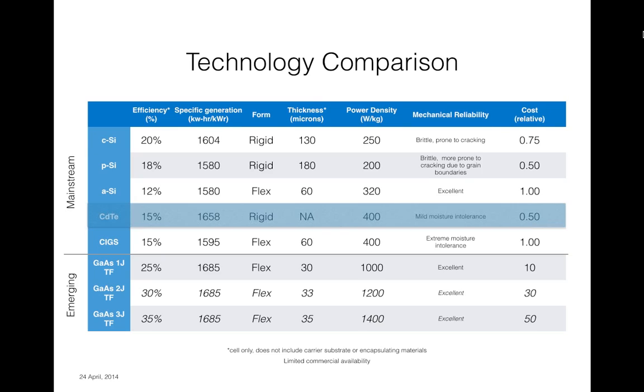Solar cell efficiencies have been moving in the crystalline silicon space at 0.1% per year for the last 10 years, and most of the major advances happened 10 or 15 years ago. And so the technology is very mature. But what you find is these thin film devices have just all this technology runway in front of them, and there's really line of sight to multi-junction solar cells that could have 40 or 50% efficiency. And so these devices then become really interesting for all kinds of mobile applications.